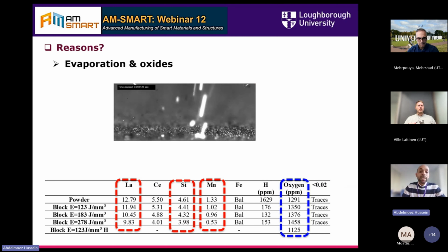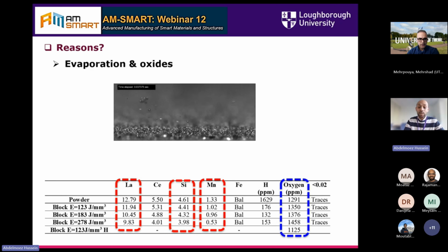The second one is the evaporation, as my colleague Ville has just said that it's very sensitive, even specifically for manganese. And for manganese here we have it. We find that the manganese starts to decrease a little bit, and even silicon and even lanthanum. So this is affecting as well the first order transition to the second order. And of course, we cannot deny the oxides formation. And oxide formation normally has an antiferromagnetic nature, which is opposite to the nature of the ferromagnetism that we are looking for.